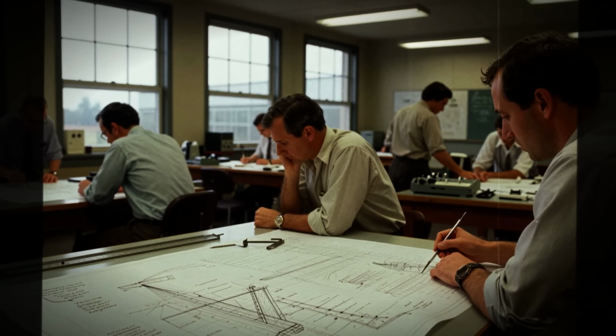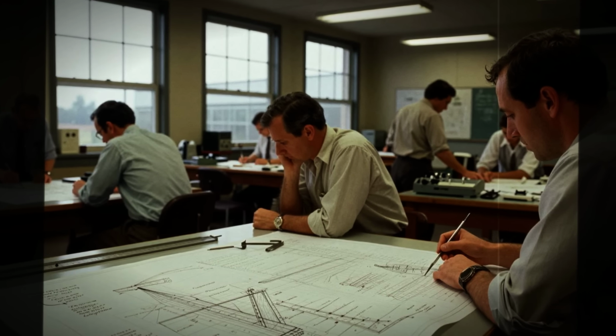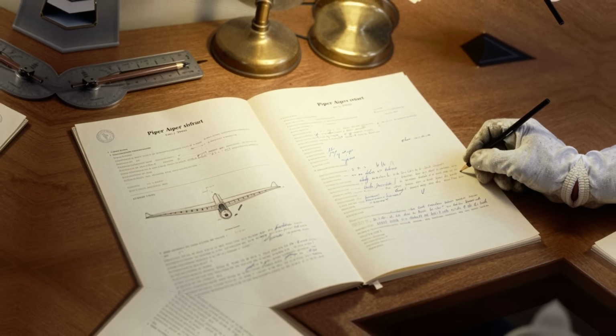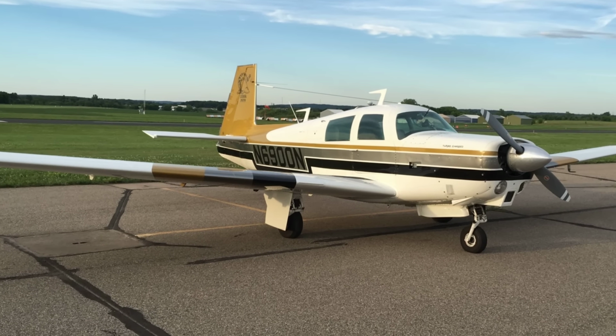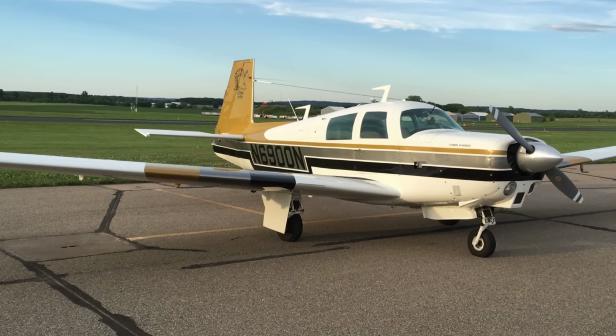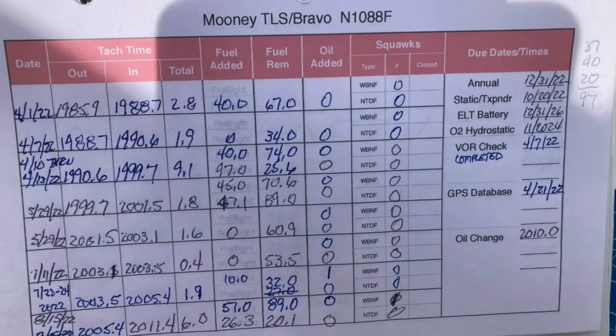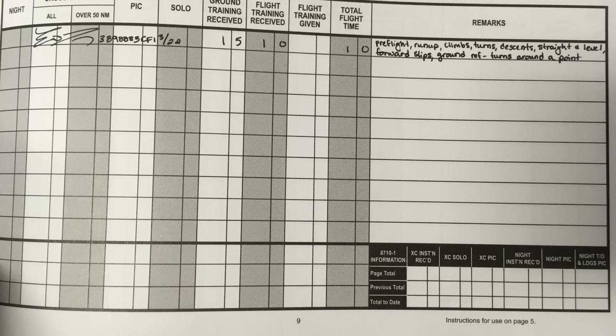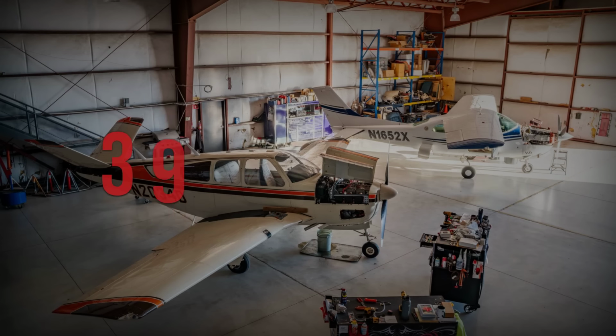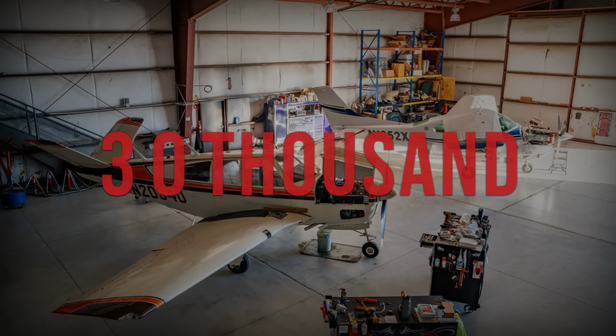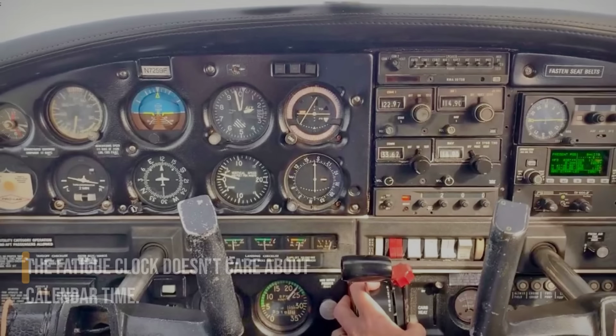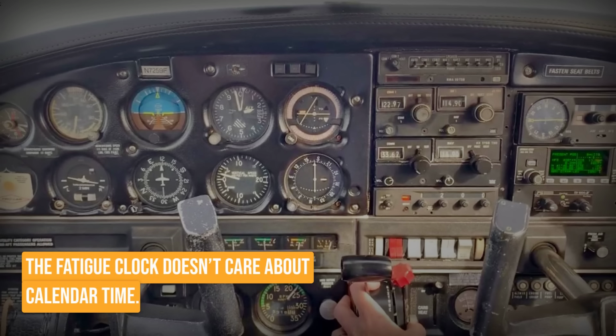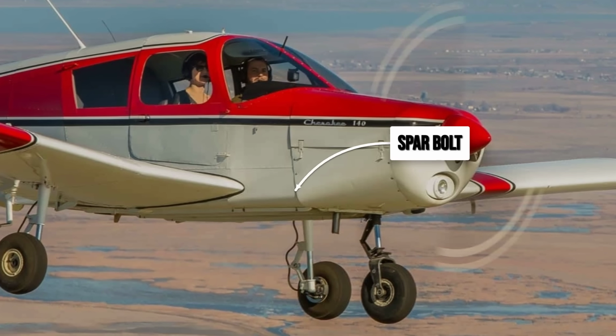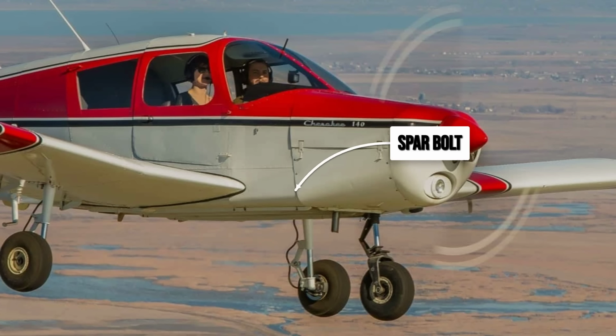Piper's engineering department stood by the original process for years, pointing to the 300,000 cycle claim and noting that most Cherokees never see that many cycles. But the numbers from the fleet tell a different story. Flight schools rack up cycles fast. Some Arrows and Archers hit 30,000 cycles in less than a decade. The fatigue clock doesn't care about calendar time. It cares about cycles, and every takeoff and landing counts.